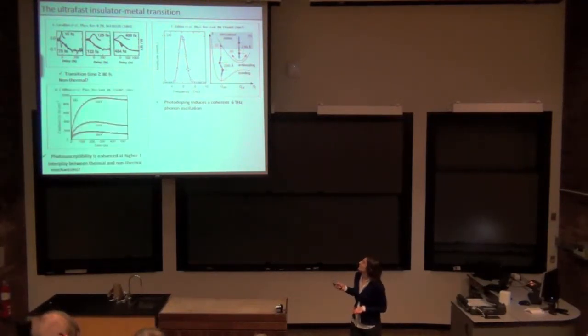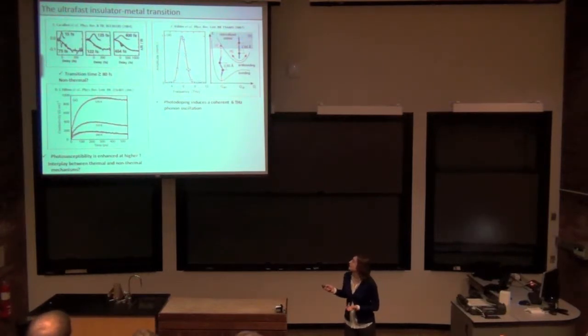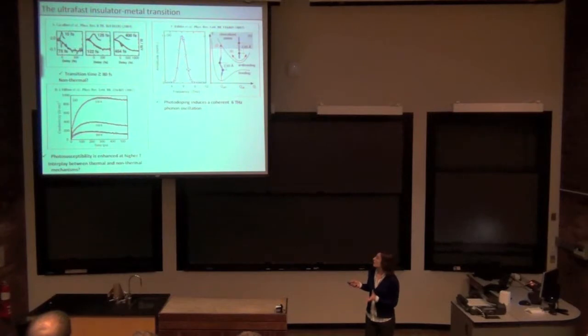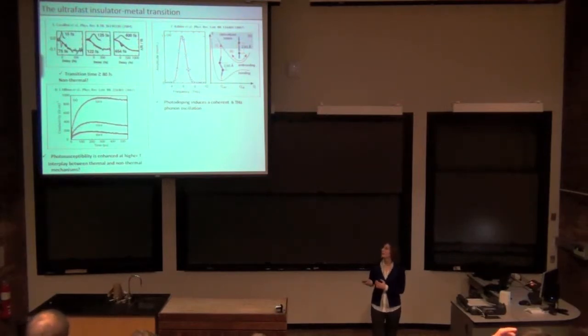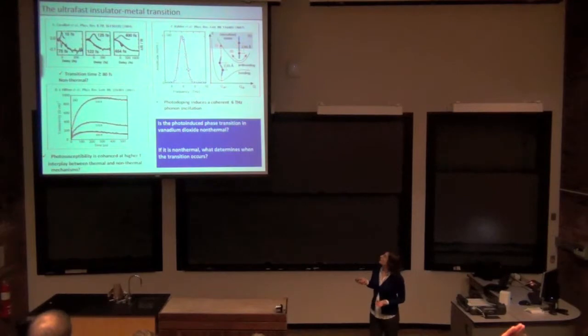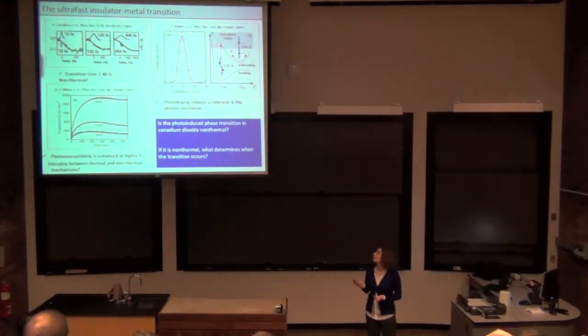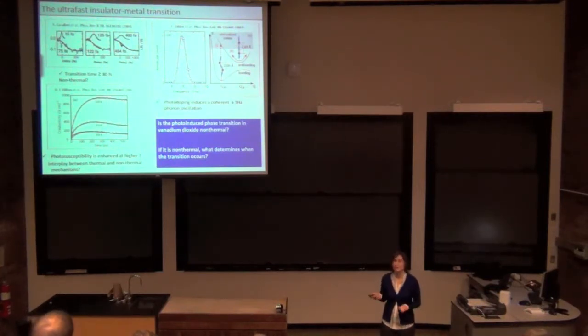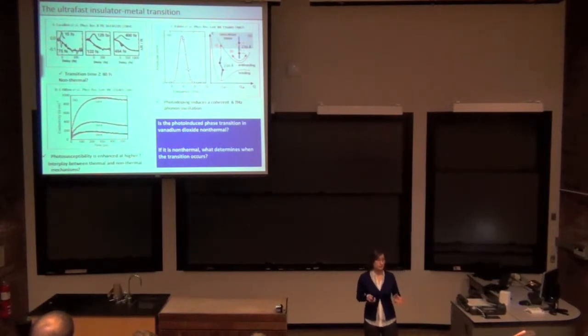And finally, the work by David Hilton, also in 2007, showed that as you are approaching the transition with temperature, the material becomes more and more susceptible to this photoinduced change, which again sort of said that, well, maybe there is an interplay between the thermal and non-thermal mechanisms. So the question remained, is this transition thermal? If it's not thermal, what is it that determines this transition, when it occurs, what is the threshold? So this is what we set out to try to answer by using terahertz spectroscopy.